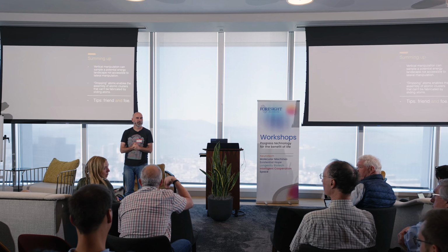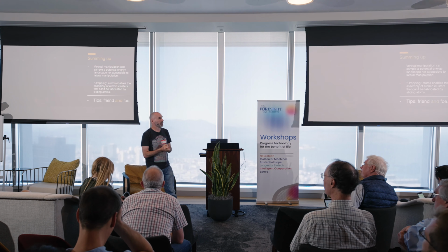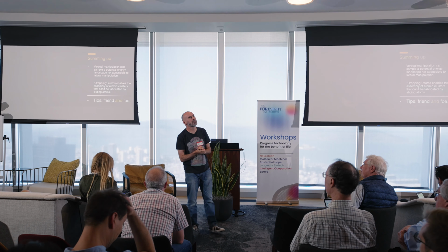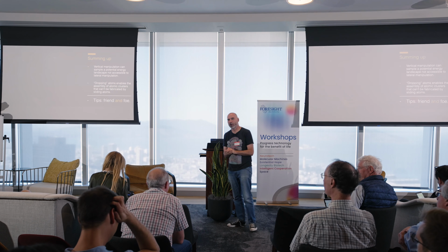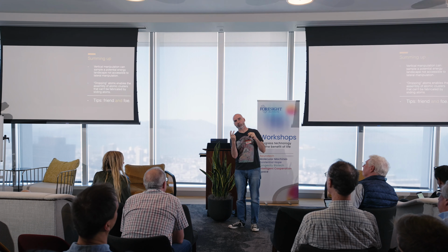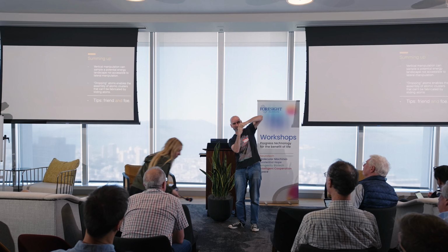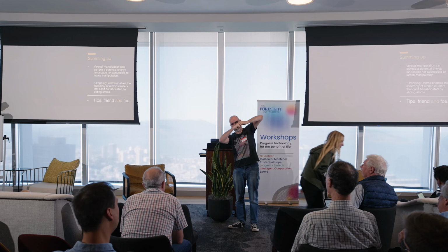Does the tip still repair if you run it backwards? There aren't enough examples, but usually what happened in terms of picking it up is that we would lose resolution. You'd end up with a double tip. The atom just wouldn't sit nicely at the end of the tip. It would go to the side and you'd clearly see a double tip, or you'd see a much greater broadening of the features.